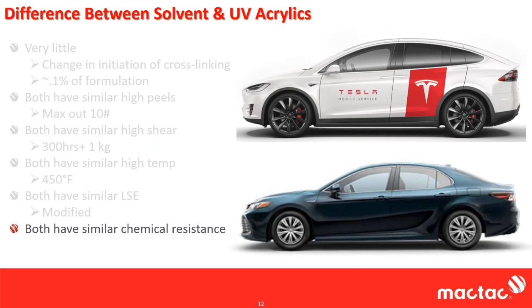And they have similar chemical resistance. Again, the fundamental difference between acrylics and rubbers, or solvent and UV acrylics versus emulsion acrylics, is that they're cross-linked. And that cross-linking is where you're getting your temperature resistance, and that cross-linking is where you're getting your chemical resistance as well. Again, both of these adhesives are cross-linked, so you're going to have similar performance for chemical resistance and temperature resistance. Both have similar UV resistance. That's more of the backbone of the polymer of acrylic versus cross-linking. But again, both could be used in direct sunlight and withstand that for years.